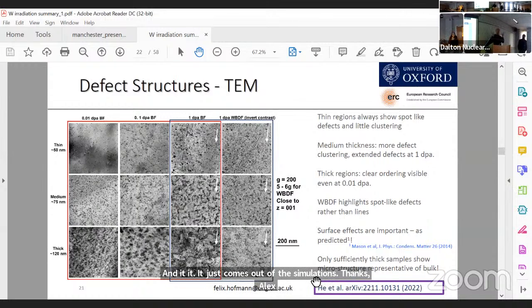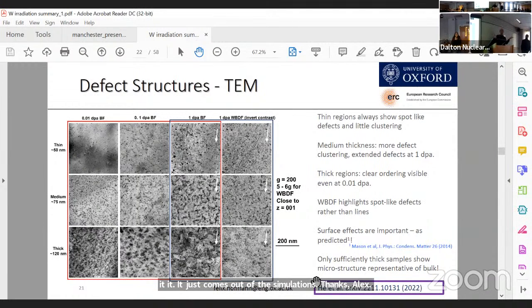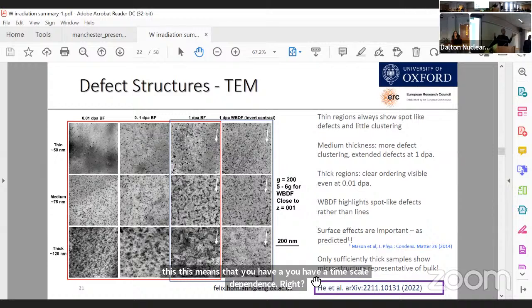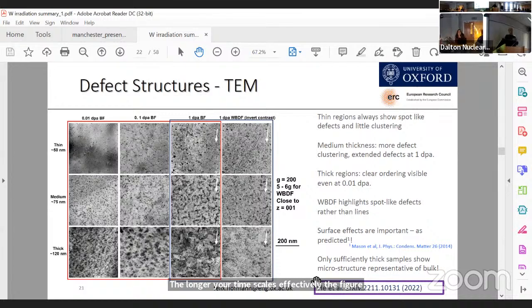Sorry, I should follow that up by saying that this means you have a timescale dependence. If you're looking at very short timescales, then maybe thin samples might be okay because you don't have time for stuff to escape. But the longer your timescales, the thicker a sample you need to move to in order to have something that's hopefully vaguely representative of the bulk.